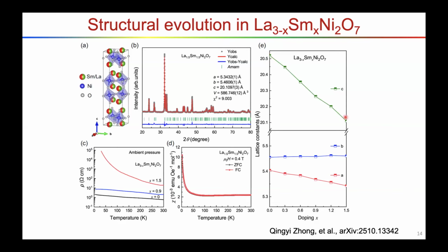So this is C and this is B, this is A. B is almost constant. A decreases a little bit, but not too much. But the sample with more samarium doping will become more insulating, even at ambient pressure. So after 50%, we couldn't successfully dope samarium. So there's a limitation for doping.